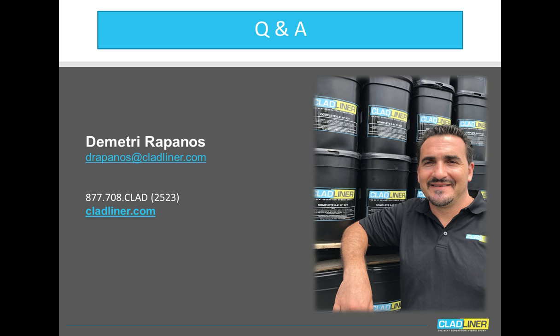How does temperature affect the application of hybrid epoxies? The way temperature affects it would be the same as it would probably affect any cementitious product, where you like to have ambient temperature between 75 and 85 degrees, and the substrate temperature, we would like the substrate temperature above 40 degrees. So in those kinds of conditions, the product would be able to be applied without any concerns.